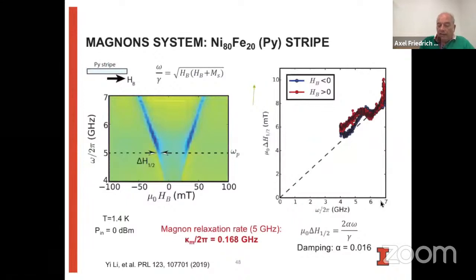So here we now look at the resonance of the permalloy stripe on top of this structure. We measure this at the same temperature with much higher power. And so here you see the resonance frequency as a function of magnetic field. And as expected, we see a magnetic field dependence that can be explained by a simple Kittel equation. Nothing surprising here. We can also measure the line width of this structure. Here, the line width is around 0.15 gigahertz, right when we are at the same 5 gigahertz. So the damping is 0.01, maybe a little bigger than 0.01. So it's not the greatest, but this is all known: when you take permalloy and you cool it down, the damping actually goes up. But it's sufficiently good for what we are trying to do here.